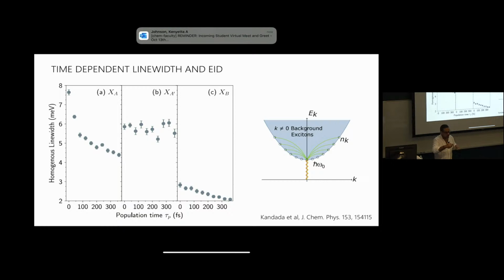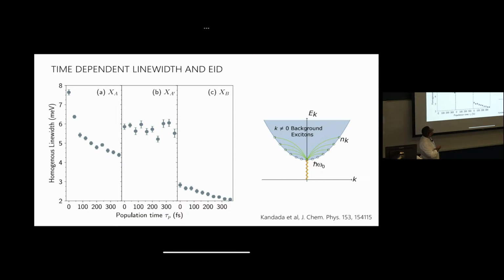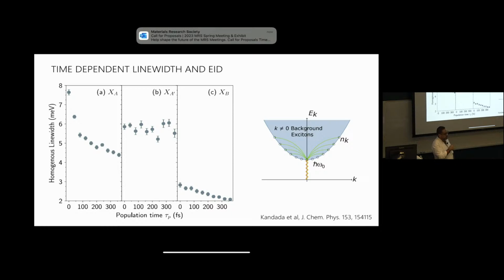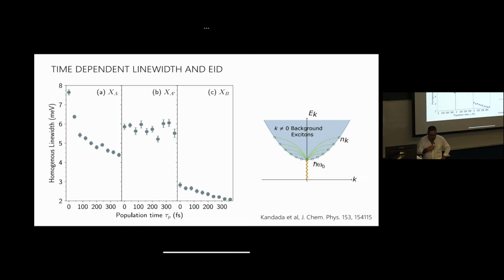enlarging. But here what you get is narrowing, because here at early time, the many-body scattering gives you the spectral broadening, this increased dephasing process. As that dissipates, this narrows, and from the dynamics of this line shape, of this line width, then you get something about the excitation-induced dephasing dynamics. So that's the kind of things that you learn. But the bottom line is they're different for XA and XB.